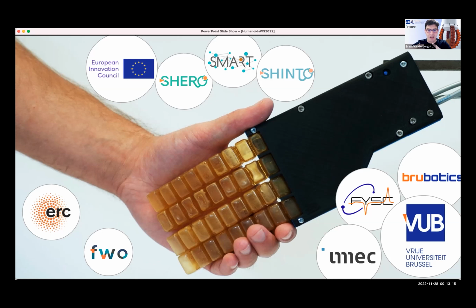But the innovation we have in our material is that you have the polymer chains and the crosslinks, but they have reversible bonds. That means you can open and close them. So if you cut the material, you get open reversible bonds, and when you bring the material back together, they reform and bind again. And that means that the network is healed again.